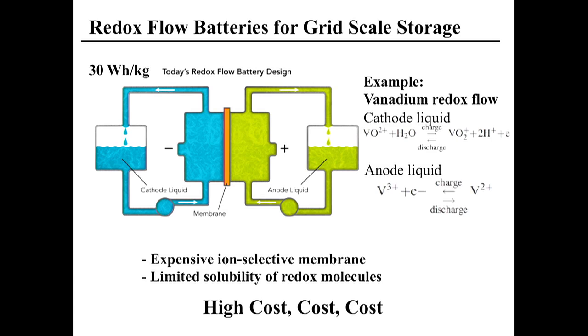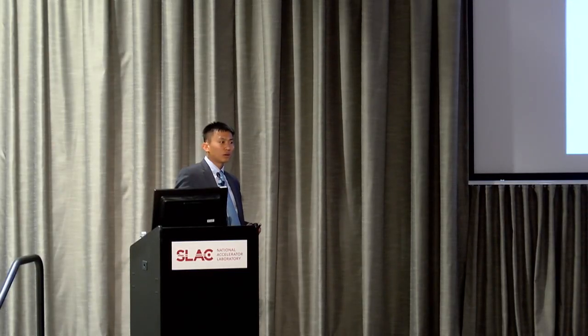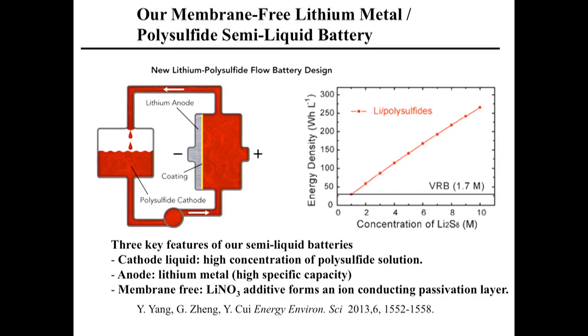So we look at this, we say, can we find a new redox chemistry that has very high solubility. So that's this guy called polysulfide. This is a really interesting story in my group's work on sulfur. I told you about the sulfur cathode. The most painful problem we are dealing with in the sulfur cathode is that lithium and sulfur react, forming so-called polysulfide compounds. They are so soluble in the electrolyte, and then we lose materials into the liquid. They cause capacity decay. Then one day one of my students came to talk to me, and we recognized, well, if the solubility is so high in that liquid, why don't we use that liquid for the flow battery?